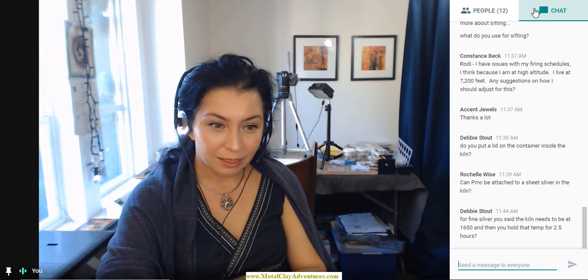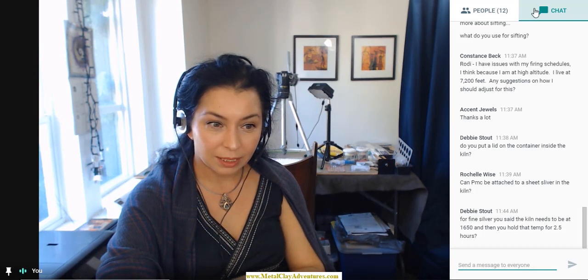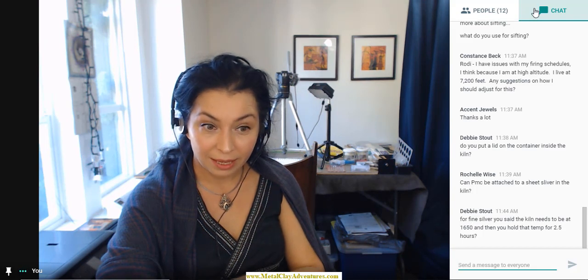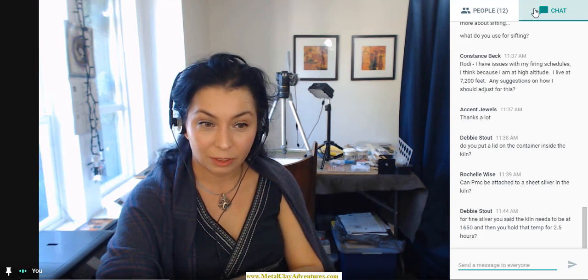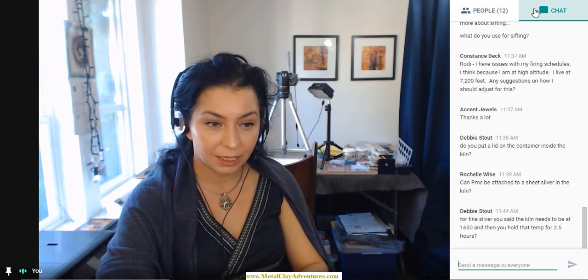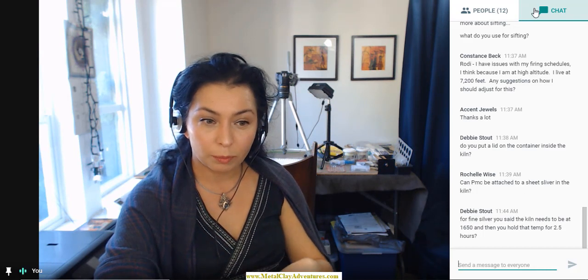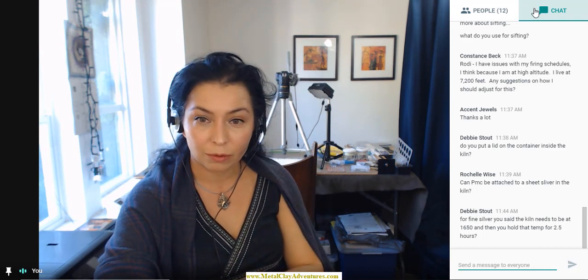JB is writing, for fine silver you said the kiln needs to be at 1650 and then you hold the temperature for 2.5 hours. Yes, for all fine silver, no matter what brand you are purchasing, the optimal temperature is 1650 and the optimal holding time is 2.5 hours.